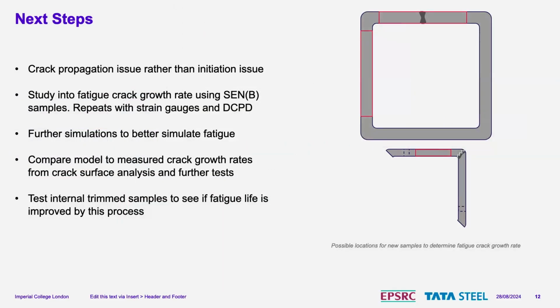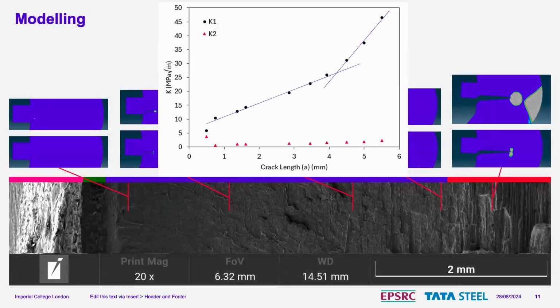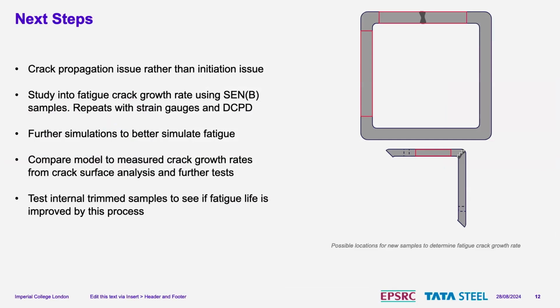So next steps. We can see that this is a crack propagation issue when we have the weld bead untrimmed. And so I'm going to do a study into the crack growth rate characteristics of this material. I've just put on here a couple of places where that material could come from. I'm also going to try and improve my simulation, because currently it's several simulations at different crack lengths, whereas it would be nice to have one that actually propagates the crack through. And then I also want to test the trimmed sample in the corner to ascertain that it is a geometric impact on the fatigue life rather than a material one.